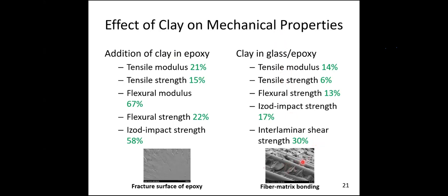If you see the bottom figure, again this is a scanning electron microscopy image of a failed sample. Because of the addition of clay, one can see a strong bonding of the matrix with the fiber. You could see, this is what we have found. Because of this strong bonding, we could get better mechanical properties due to the addition of clay in the glass epoxy composite.